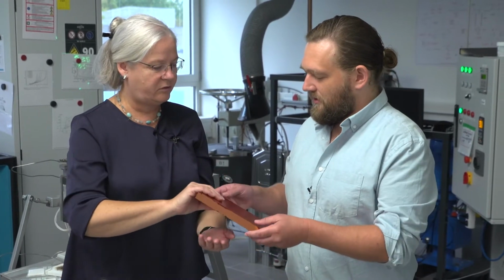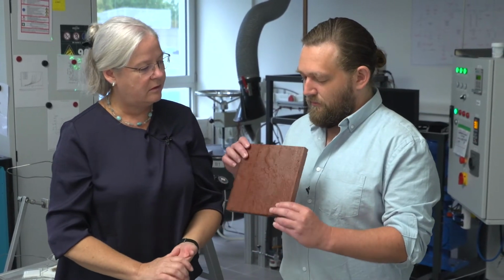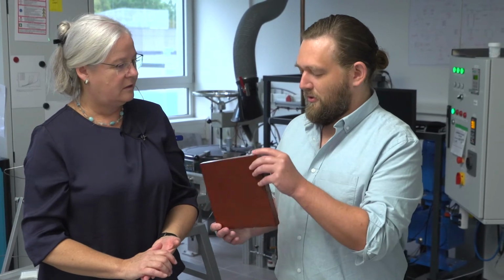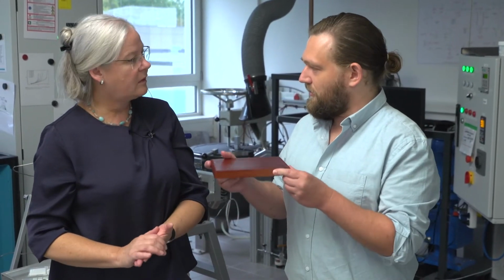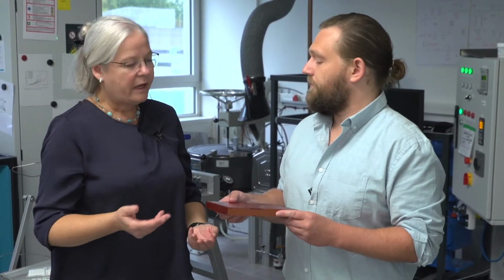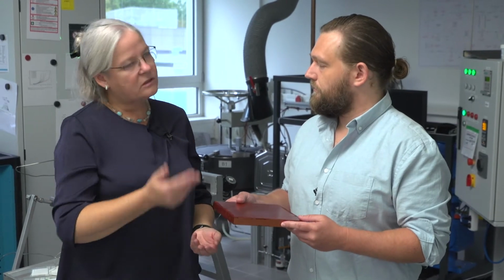Can I hold this one? Yes, for sure. It's very light, yeah. That's a very nice aerogel. Look at it. It's very big. So you must have some big autoclaves that you're able to dry materials like this in. Yes, but if you use a standard recipe, as we call it in our labs, then we do not need this. Oh, so you can ambiently dry. Yeah, we can ambient dry them, and this is not for thermal insulation because the thermal conductivity of this material is around 60 milliwatt per meter Kelvin.